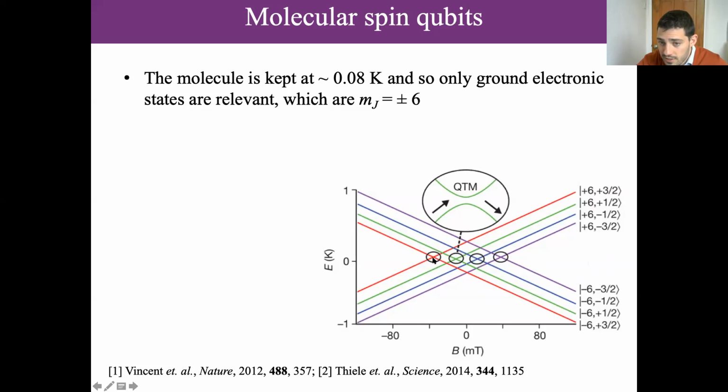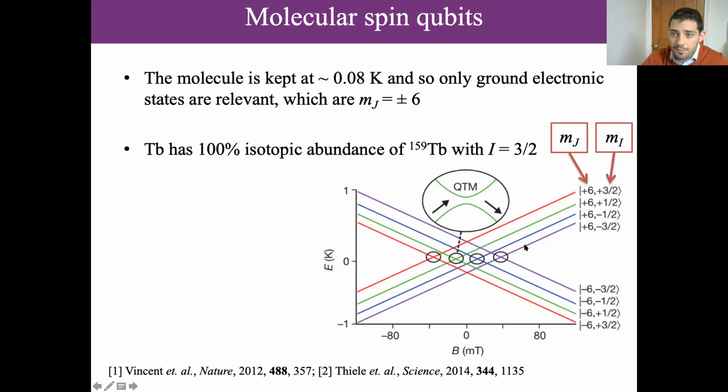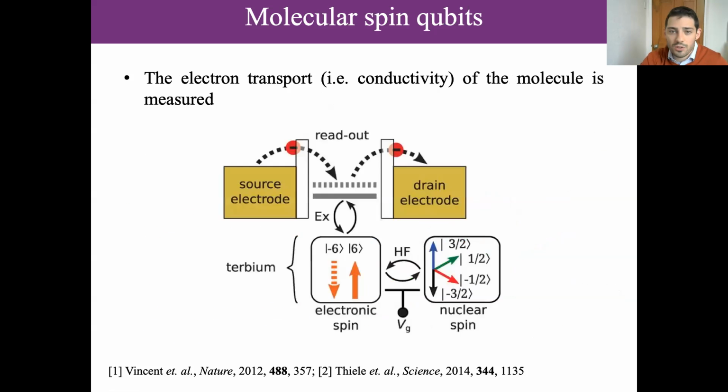And at each of these avoided crossings for these different hyperfine states, you get quantum tunneling. This is essentially when you have a very fast change in magnetic moment of the sample as you traverse adiabatically this avoided crossing. So you get essentially a spin up here going to a spin down on the other side. If you sweep slowly enough, you get this transition. Sorry, this is for my students, so I've got a lot of stuff.